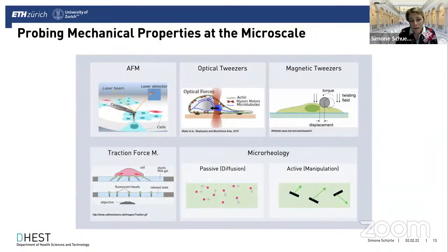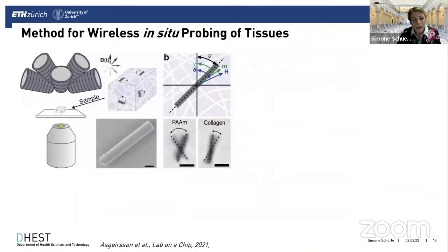The tissue mechanics vary across length scales. Shear moduli measured from bulk rheology at the macro scale versus single fiber analysis of pulling on single collagen fibers yield a wide span of values. We're particularly interested at the cellular scale — what shear moduli does a cell embedded in this matrix actually experience? There are different techniques to assess microscale mechanical properties: atomic force microscopy, optical tweezers, magnetic tweezers using spherical particles, traction force microscopy, and microrheological assessment. We're interested in applying magnetic fields — but not just with spherical particles. Instead, we use microcylinders as little microprobes, which through shape anisotropy give rich information about tissue mechanics.